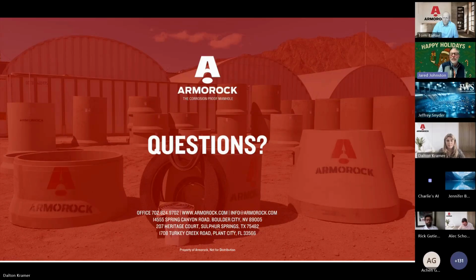And the part that made me laugh is he says he's burning through drill bits. He's referring to the strength of our product. Our product is strong. In fact, as our strengths show, it's typically 3 to 4 times stronger than concrete. And so, yes, you can burn through things. As far as that, it's never going to get weaker. We are the strongest in the industry. It's going to stay there. As far as wearing out your equipment, just slow it down and let it eat a little longer. It takes about a third longer to core through our product than it does concrete, and drilling needs to be the same. Slow it down and it will be a little easier.